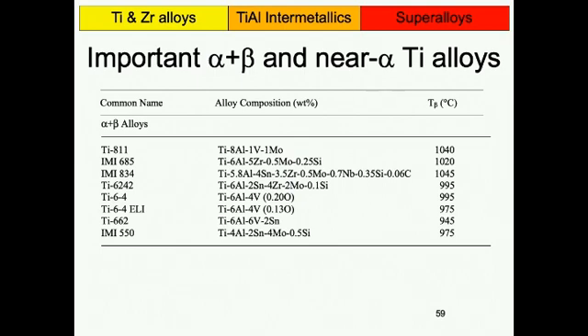And you can also see that even 6-4 has a low interstitial variant. So you can see the oxygen drops from 0.2 to 0.13, or even lower actually. I think these numbers are a bit older. I think generally the oxygen levels are much lower these days in both types.